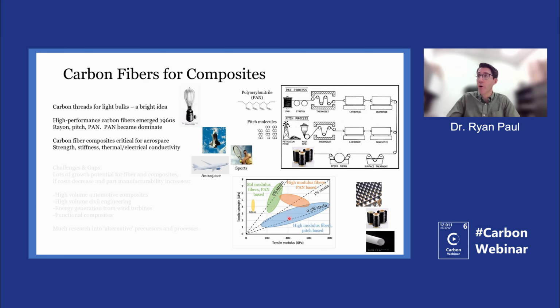The amount of strain that you can get to failure is very different. The high modulus or pitch-based carbon fibers tend to give a very low strain. There are high modulus and standard modulus PAN-based fibers, which can give different strain to failures. And this is contrasted versus glass fibers. Glass fibers are widely used in some applications as well. They have a much lower modulus than is available with carbon fibers, but they can give an acceptable strength, and they have a lower cost, which can make them very competitive. So what kind of fiber you need depends on what kind of application you have and what your allowable cost is. But from a structural perspective, there's a wide space available where different types of carbon fiber precursors can fall.